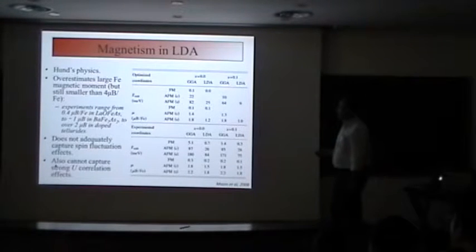But experiments are substantially below this, at least in a couple of compounds. The 1111 compound is about half a Bohr moment, the 122 about 1 Bohr moment, but higher in the tellurides, and even higher still with the new compound, the potassium XY2 or 112, that was discussed earlier this morning.